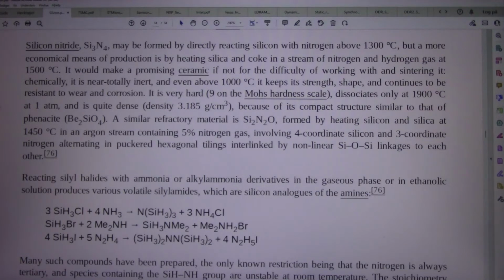at 1 atm, and is quite dense. Density 3.185 g/cm3, because of its compact structure similar to that of phenacite, Be2SiO4. A similar refractory material is Si2N2O, formed by heating silicon and silica at 1450 degrees C in an argon stream containing 5% nitrogen gas, involving 4-coordinate silicon and 3-coordinate nitrogen alternating in puckered hexagonal tilings interlinked by nonlinear Si-O-Si linkages.